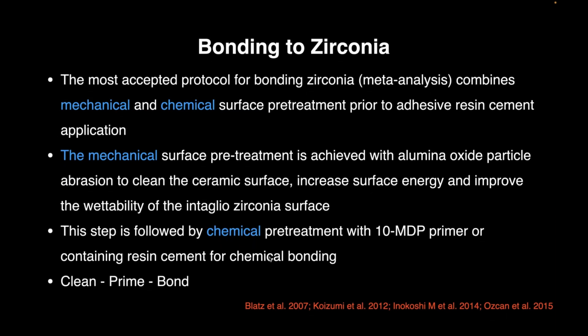So the mechanical surface pretreatment is usually achieved by aluminum oxide particle abrasion to clean the ceramic surface, increase surface energy, and improve the wettability of the intaglio zirconia surface. This step is followed by the chemical pretreatment, which is the 10-MDP primer or 10-MDP containing resin cement for chemical bonding. So we have these three steps that are known as clean, prime, and bond, or the APC, which is air particle abrasion, primer application, and composite resin cementation.